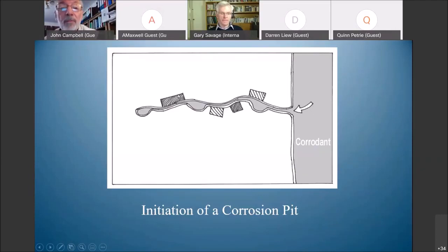And of course, if this is a bifilm, these are some of the precipitates that form on bifilms. They like to form on the bifilm because the volume change and the shape change are easily accommodated by the gap between the two films. And in doing so, the precipitate here actually prizes open the bifilm a little bit. So as these grow and they prise open the bifilm, so you get corrodant sucked in. And the corrodant now can corrode very, very readily because this is a really good corrosion couple. So there's a good chance of having very active corrosion couples. And so corrosion happens from the inside of our metal because the bifilm is in.